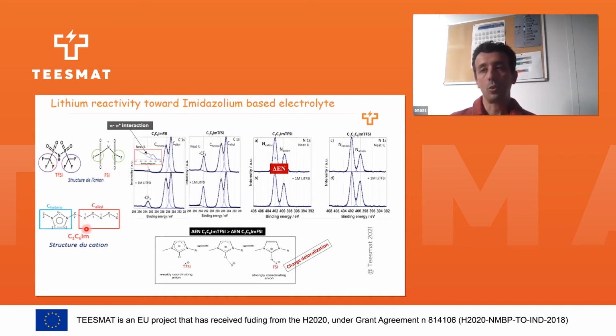In this case, to make it an electrolyte, you have to add salt. The salt in this case is LiTFSI. Here we can see the reference sample XPS, before adding the salt, in the upper spectrum. This is the carbon peak of C1C6im FSI, that means C1C6im with this kind of anion. C1C6im TFSI is with the second kind of anion. We can see that the carbon peak has two signatures. The first one is the carbon related to the alkyl group. The second one is the carbon related to the aromatic ring.